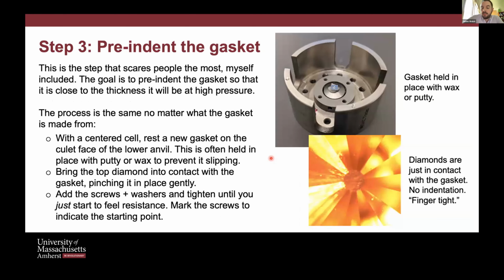Okay, so the next step then would be to pre-indent the gasket. This is an important step. Stas gives some details on why. I'm showing here a rhenium chip. This has actually already been indented by the looks of it, but originally this would just be a 250 micron thick square rhenium chip. We rest that on one of the anvils, and you can see there's some wax that keeps it in place because it's easy for that to fall off. And that's a very good way to break diamonds, when that falls off and you don't realize, and then you close the cell up. So the wax keeps it in place. What we are trying to do is compress that between the two anvils so that we get a pre-indentation. So rest the gasket onto that lower anvil, bring the top in, and then look through the microscope, and you'll see something like this.